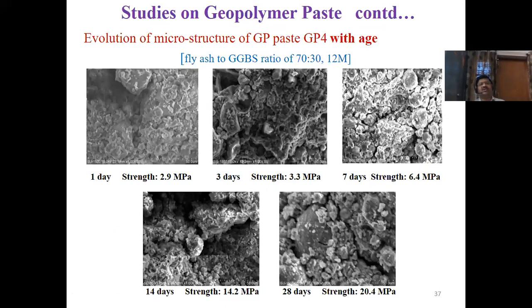See here. So we have made some correlation between the strength and microstructure. So it is 1 day, 3 days, 7 days, 14 days, and 28 days. So here, strength at 1 day is 2.9 MPa. Next 3 days it is 3.3 MPa. 7 days it is 6.4 MPa, 14 days it is 14.2 MPa, and 28 days is around 20 MPa. So apart from the strength, age and strength, we also captured the microstructure of the geopolymer. So if you see these 5 microstructures, there is refinement of microstructure. So which is giving confidence of developing the strength.